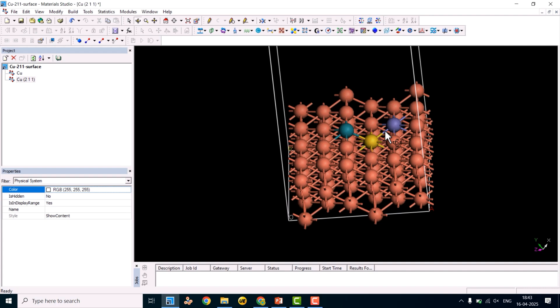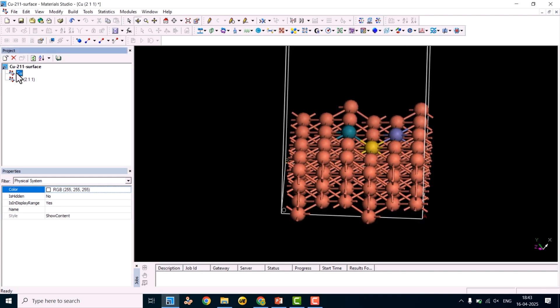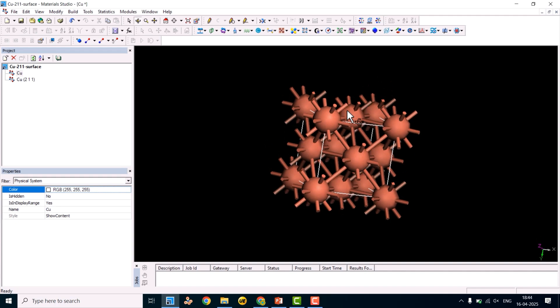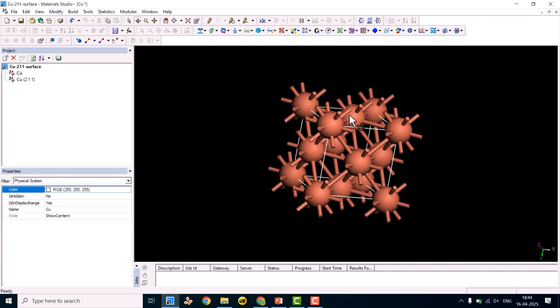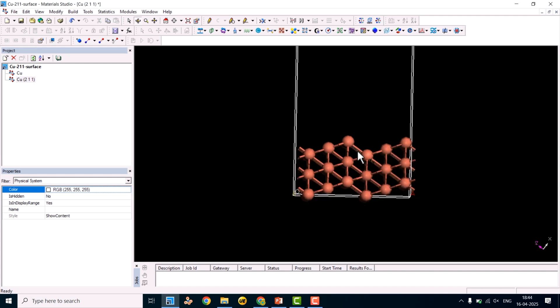Likewise, you can make any single atom alloy on the surface for your catalytic transformation studies. Before doing any catalytic conversion, first optimize the copper bulk structure with ISIF=3, then take the optimized POSCAR and CONTCAR files, convert them to CIF, and cleave your surface in Materials Studio. After cleaving, you need to sort the atoms along the Z direction so you can easily fix the bottom layers and relax the top layers. I have made another video for that VASP setup which I will put in the description box.